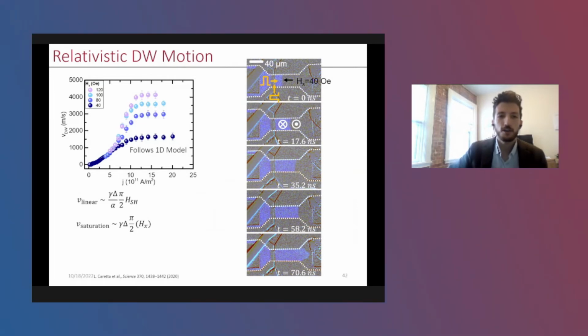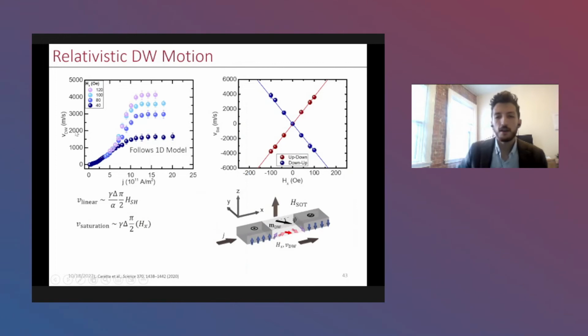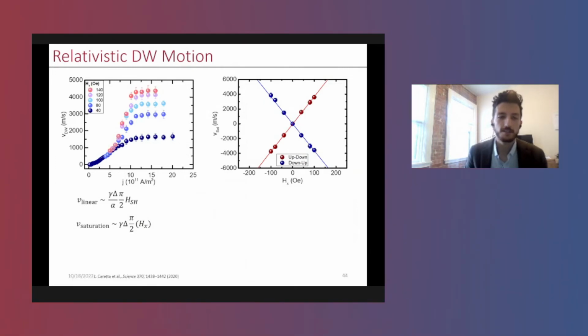So the larger the in-plane field that you apply, which is shown here in the legend, the higher this plateau velocity. And what you might notice is the y-axis of this plot is actually quite high. We're in the thousands of meters per second with these domain walls. And in fact, on the right here, I've plotted the saturation velocity, or this plateau, as a function of the in-plane field. You see it's indeed quite limited. What's interesting, though, is if we keep increasing this in-plane field, these curves begin to stack up on one another. And in fact, this saturation or plateau itself does not get any higher. The plateau itself plateaus, you can see on the right.